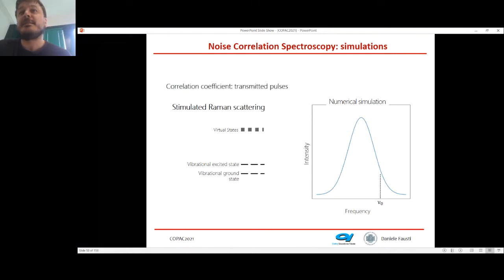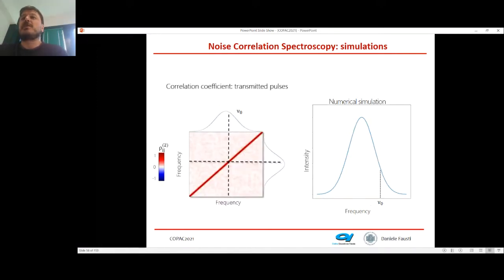And why is this the most interesting situation? The idea is quite simple, and this is the first experiment we did. We tried to measure some Raman scattering, as in the previous speaker. In Raman scattering, you destroy a photon at one given frequency, and you create a photon at a frequency which is shifted with respect to the central frequency by the frequency of the phonon which mediated this scattering. If you start from the situation with these frequency uncorrelated fluctuations, as I've shown you before, what can you expect? For my pristine pulse I have correlations only between one frequency and itself, but if I have a Raman process,